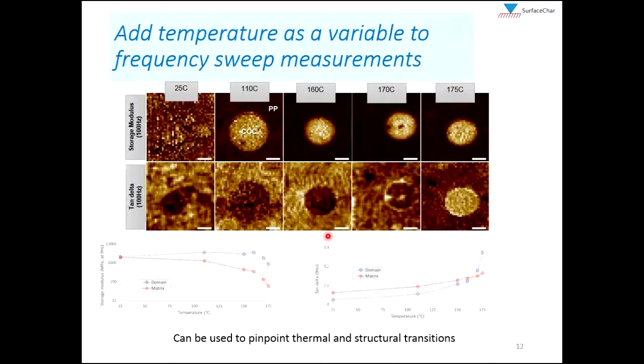So now you can add temperature as a variable to these frequency sweep measurements. Again, this is what is done a lot in the conventional DMA community. So here we had a different blend. We had a blend of polypropylene, that's the matrix, that's in the background, and then a domain of cyclic olefin copolymer here in the middle. And so we mapped now the storage modulus and loss tangent, again at 100 hertz, as a function of temperature, from room temperature all the way up to 175 degrees C.